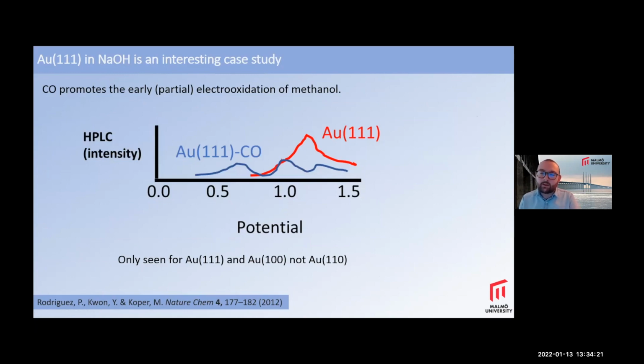Why is this surface interesting for methanol oxidation? Well, one reason might be that there's quite a few studies showing interesting electrocatalytic properties of gold surfaces towards methanol oxidation. So, for example, it's been shown that CO promotes the early partial electrooxidation of methanol. So if you look at your HPLC intensity with CO on the surface, you already get some oxidation of the methanol down at lower potentials. Whereas with just the gold 111 surface, most of the oxidation happens at much higher potentials.